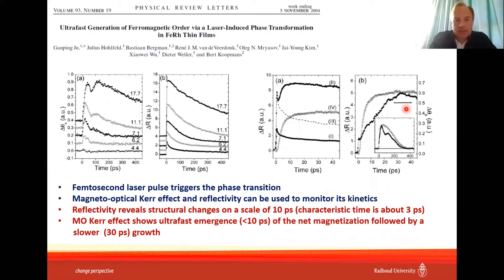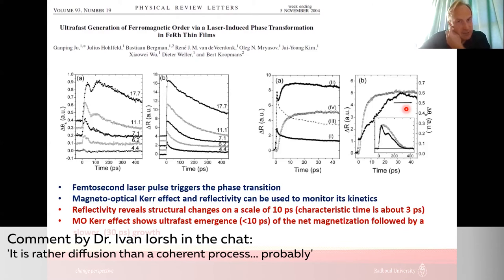Yes, thank you very much. That's a very good question. Of course, reflectivity basically probes refractive index change. And if the lattice expands for about 1% in this material, reflectivity should change upon lattice expansion. So where does the time scale come from? Well, the time scale comes from the speed of sound times the thickness of the film. So this is the characteristic time for the lattice expansion. So the thinner the film, the faster this reflectivity change will be observed.